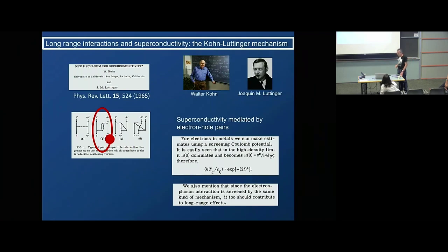Then you have to worry about longitudinal acoustic phonons as well, because this diagram, this RPA bubble, implies you're looking at electron-hole charge fluctuations. A charge fluctuation can couple through the deformation potential to longitudinal acoustic phonons. So the calculations I'm going to report not only include electron-electron interactions, they also include, by definition, LA phonons, because they are unavoidable if you start from this point of view.